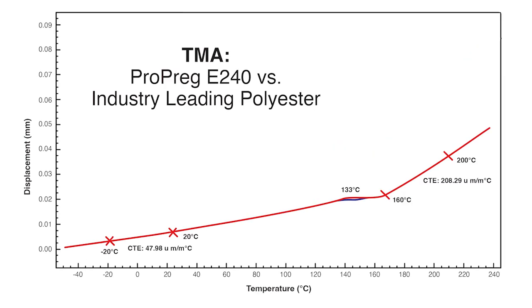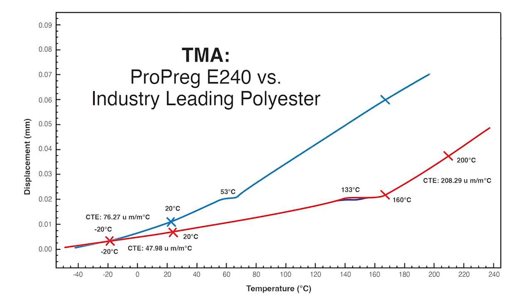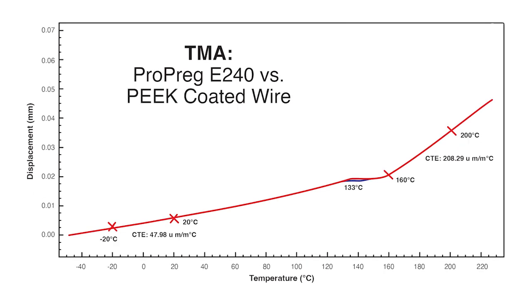When we overlay a polyester onto the graph, you can see a distinct difference in the TG. The TG of the polyester is significantly lower than E240 at approximately 53°C. A lower TG indicates a lower degree of cross-link density, which yields lower thermal stability and reduced chemical resistance. Additionally, when you overlay the TMA of E240 with PEEK, you see that they have a much closer pre-TG CTE. Another thermal analysis tool that is used to identify potential improvements to a polymer is TGA.